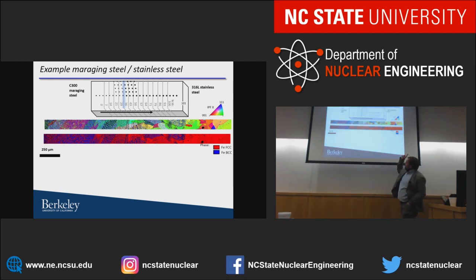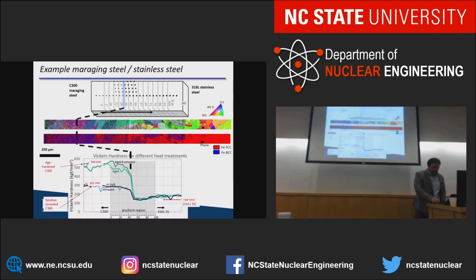But then we do a hardness trace along that length and measure the hardness along this transition region. And it turns out that's not continuous. So you would think that the hardness is a continuation between one and the other. But it's not the case at all. The hardness actually stays the same on the FCC side, pretty good, even though you add some BCC. At some point, however, you reach one composition where the hardness suddenly jumps. And if you heat treat it right, then it jumps even more. And you get quite a substantial mechanical property increase. But it's not continuous. It's a jump from one layer to the next.